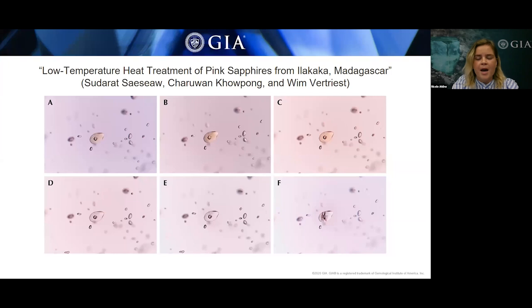However, when looking at monazite crystals, they did actually observe that they went from this nice orange brown color that you can see in box A to near colorless. So pictured here, you can see the range of that monazite going from that nice orange brown to colorless. Pictured in box A is that pre-heat treatment, and it was identified using Raman spectroscopy.